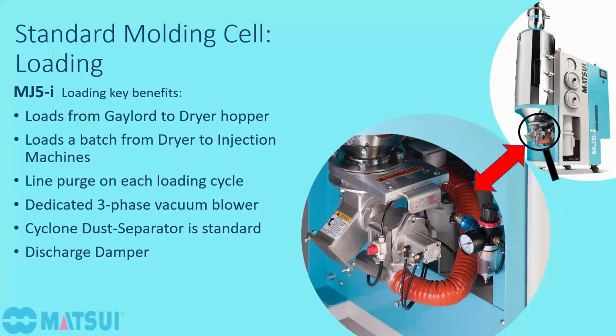Also, something else that we have that's a real nice feature is a normally closed discharge damper. And whether you're looking at our dryer or someone else's, this is a nice feature to make sure that the dryer will have. It's placed at the bottom of the drying hopper, and it's controlled by a timer that you can adjust based on your injection machine throughput and shot size. So when the injection machine calls for material, that valve will open based on whatever the timer is set for, and it will discharge material. If the timer is set for 2 or 3 seconds, it'll discharge material for 2 or 3 seconds and then close again. Then vacuum is applied to convey all that material to the vacuum receiving hopper on the injection machine.